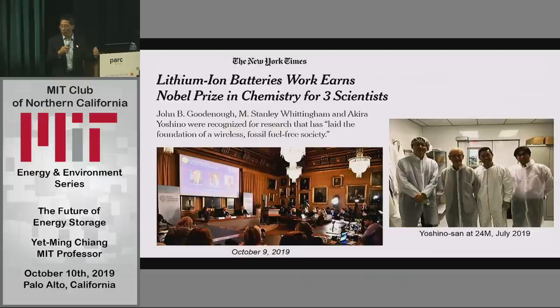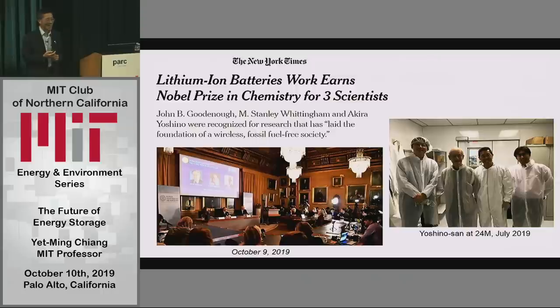And the problem with lithium metal was that it formed something called a dendrite, which had this unfortunate behavior of causing an internal short circuit, which combined with a flammable liquid solvent, led to the expected outcome. So this is the example of the first to market getting crushed. And so the innovation that is the lithium ion battery was actually what Stan demonstrated, but without the lithium metal. Yoshino-san's contribution was recognizing that carbon was an ideal host to insert that lithium into, so that you didn't actually get the metal itself.